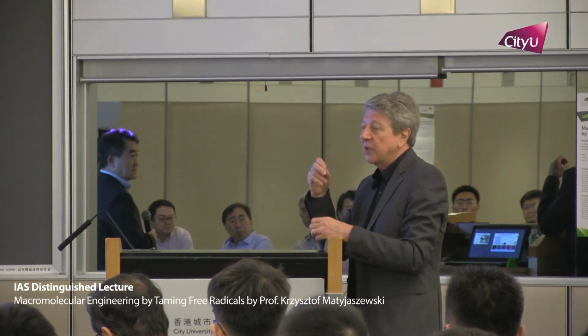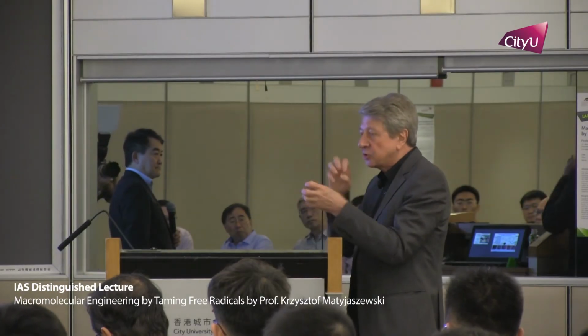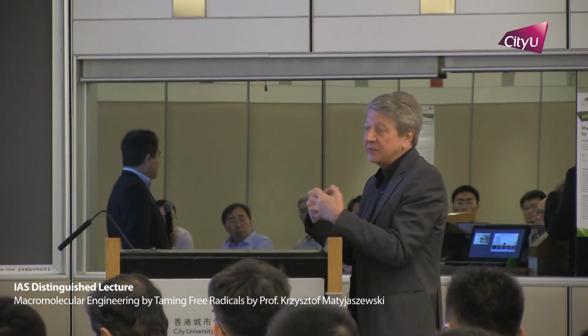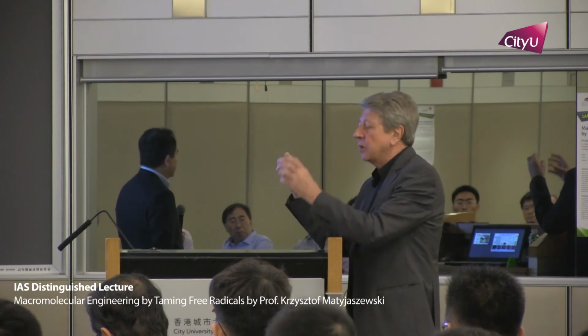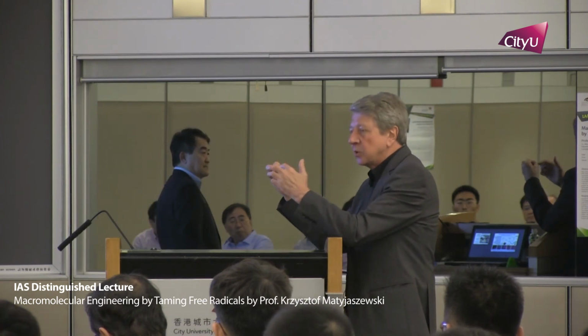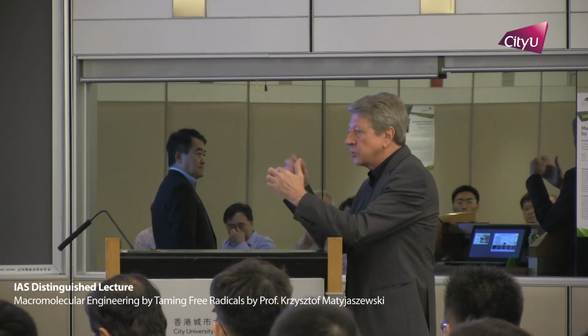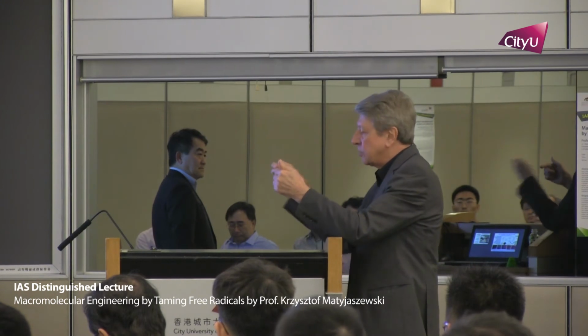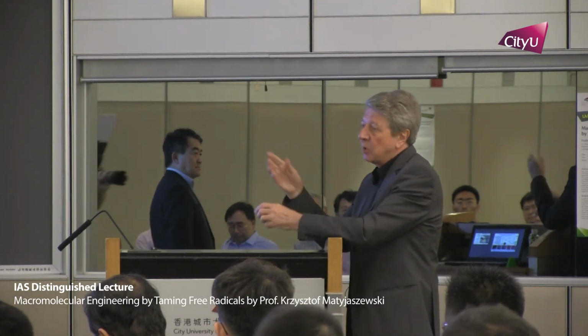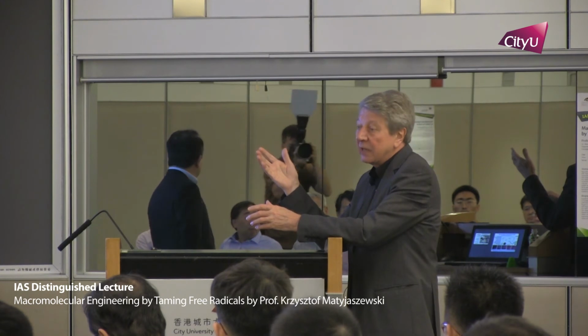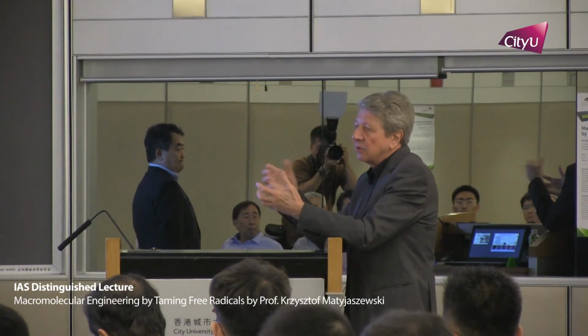For example, if you make a plexiglass, you may smell a little bit of the methyl methacrylate, although it's already a glass. Meaning the chains cannot move because they are trapped in a glass state completely. But if you have a small molecule reacting with polymer chains, in that case this diffusion control limit is smaller, because although the polymer chain is immobilized, this small molecule can come very fast, whether it would be a monomer or the activator. But eventually, if you cross a certain viscosity or glass state, this reaction slows down.